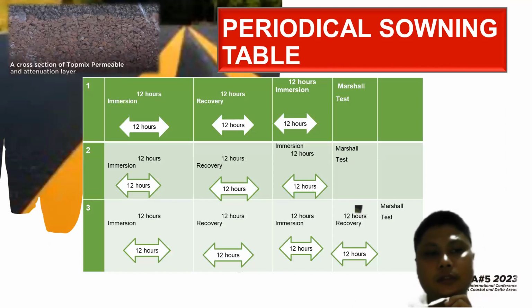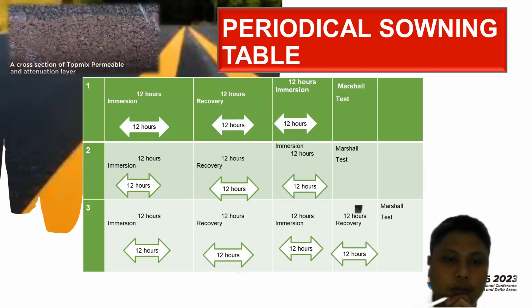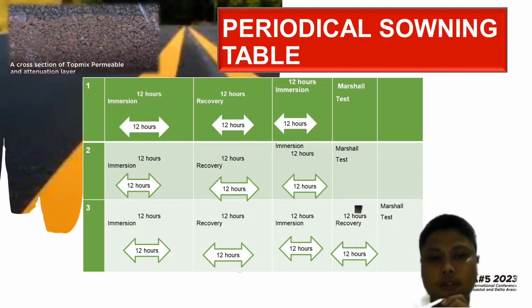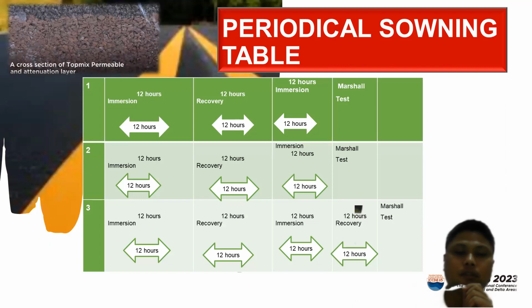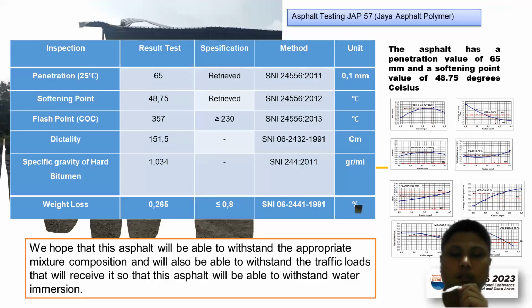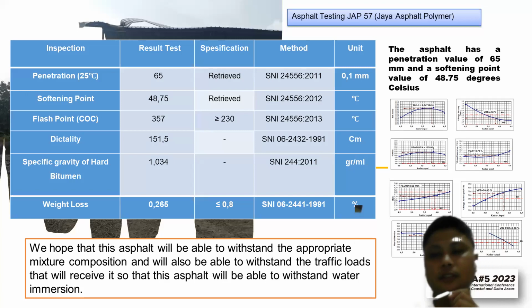In the table, we can now do 12 hours of immersion, 12 hours of recovery, 12 hours of immersion, then Marshall testing, and so on. The parameters are stability, flow, void in mineral aggregate, void filled with bitumen, and Marshall quotient.